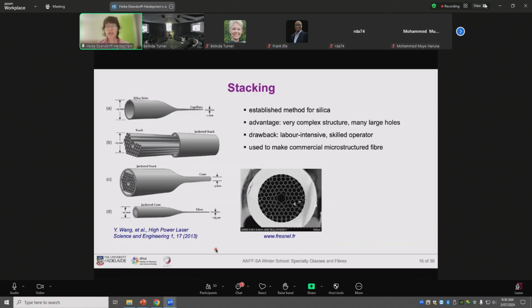Another technique which is used commercially is the stacking technique. It's a manual technique, but it is the technology for making silica microstructured fiber preforms. It takes silica tubes and silica rods. They are stretched to thin capillaries and thin rods, which then are stacked according to the pattern that is wanted. One of the most complicated fibers made commercially in this way is the so-called kagome fiber.